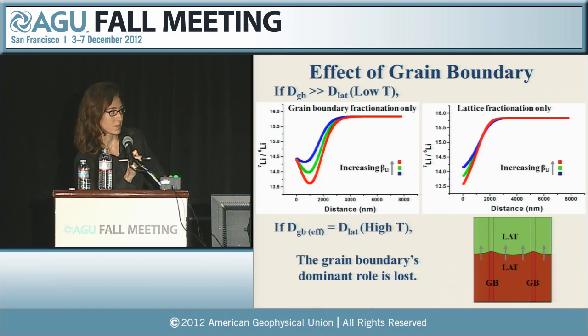If the grain boundary diffusivity is about equal to the lattice diffusivity, which is sort of equivalent to a high temperature environment, let's say, similar to the temperature at which the experiments have been run, then the grain boundary loses its dominant role in controlling what the lattice isotopic composition will be. The reason why this happens is there's so much diffusant that's being lost to the lattice that the grain boundary diffusivity is basically equal to the lattice diffusivity.